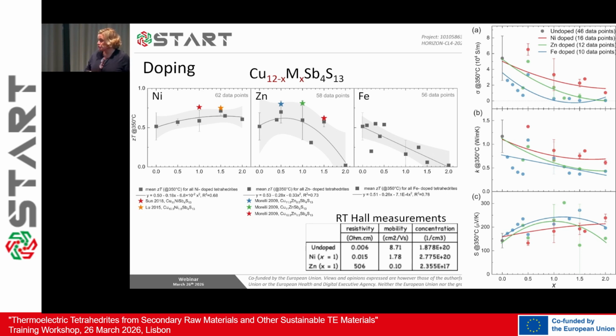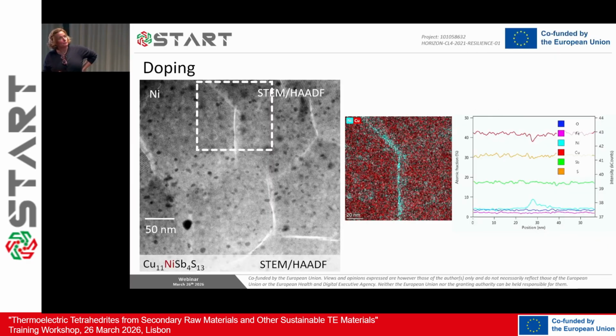We managed to do something, but it was very difficult because there's only 2 or 3 papers in the literature with Hall measurements for tetrahedrites. We managed to measure. It makes sense, the results we had, but again there's not so much data in the literature.